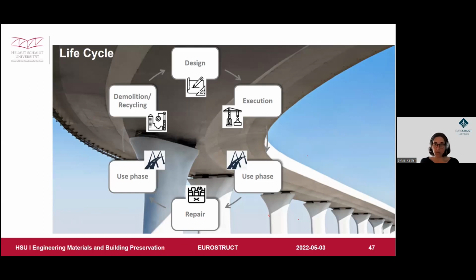It would be nice to have such data, definitively, but here we have to keep in mind that normally we have to inspect those structures within 1 day, or 1.5 days. You're limited to the downtimes of the structure, and you have to be fast. And this is the big advantage of the half-cell potential measurement method. You can do it relatively fast. You can scan it, and then you get a good overview about the whole structure in order to get an idea about the spatial variability of your corrosion damage.